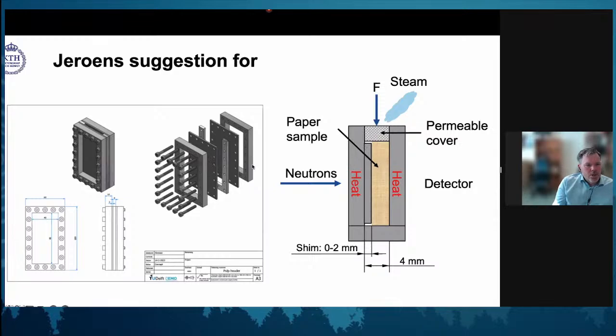The system is such that in between, in this wafer, we can put in the fiber mat that is wet. We can't apply pressure, but we can put in something called shims, so we can restrict the dimensions, which of course implies a certain pressure. So we can have different volumes with the same amount of fiber. We have a holder so that this sheet doesn't by some means fly away when you generate steam. And we can heat the system.